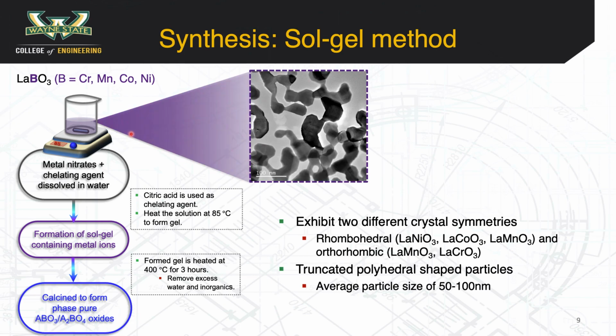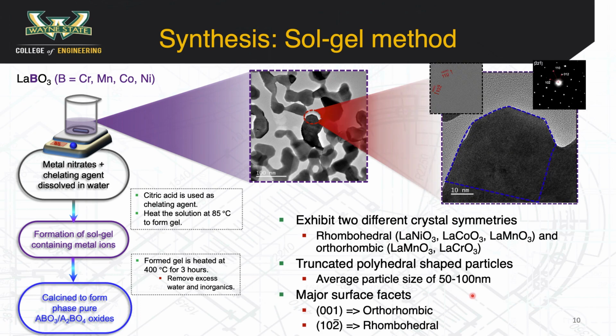A typical sol-gel type synthesis results in the formation of polyhedral shaped particles with an average particle size of 50 to 100 nanometers. We then combine these studies with some selected area electron diffraction measurements from a transmission electron microscope to identify the surface structure of these oxides. It is observed that on a rhombohedral surface, a (1,0,-2) transition metal oxide terminated surface is dominant, while on that of an orthorhombic structure, a (0,0,1) transition metal oxide surface is found to be dominant.